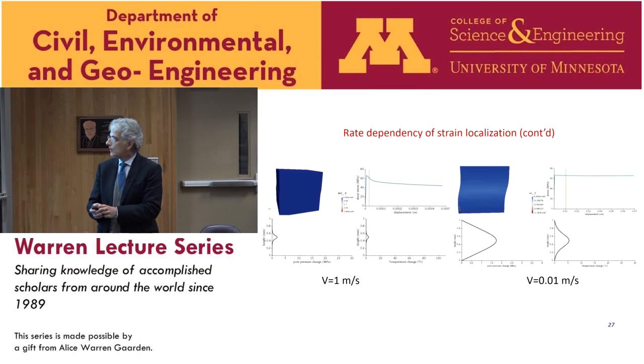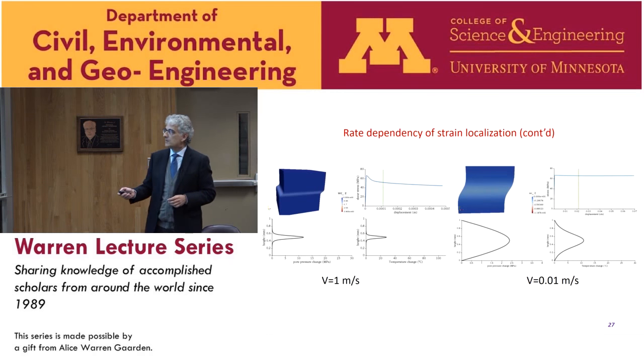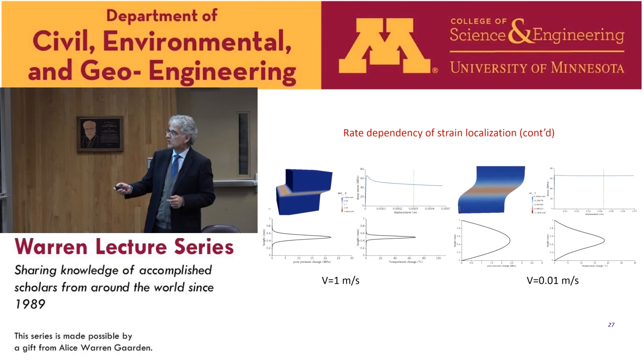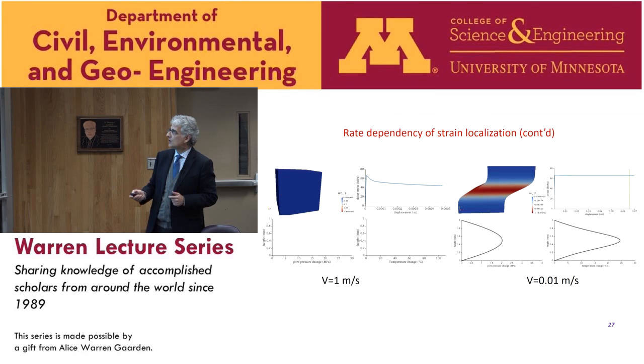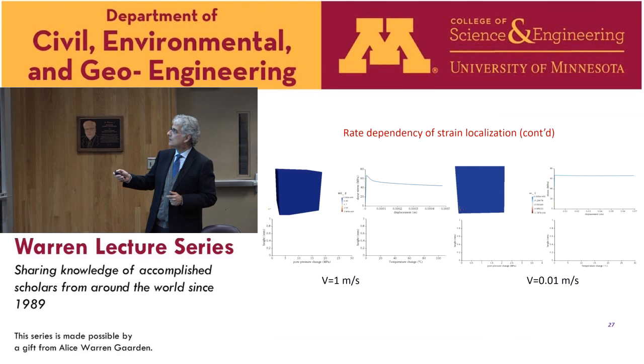And with a velocity of 1 meter per second, you see that the system is less localized, the pore pressure change is much smaller, and we even have a delocalization. So you see that it's a whole process, and there is softening, but it's so small that we don't actually see it. So what I want to emphasize here is the rate effect that we obtain through the diffusion process that controls the localization.